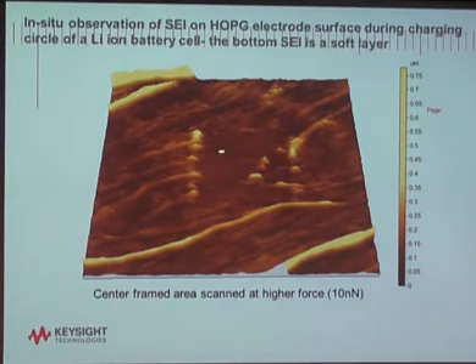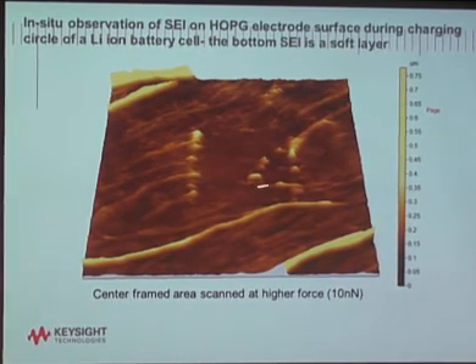And that's what we did. We apply a little bit higher force, about 10 nanonewtons, scan a small size, and scan a large area again. We actually push them flat. So that's evidence that these wrinkled sheets are actually not a solid material, but some soft material. Only by applying force can you squeeze out those lithium ions inserted in the graphite sheets.